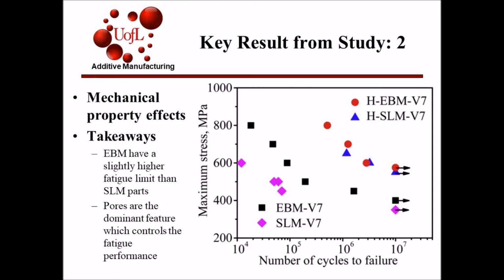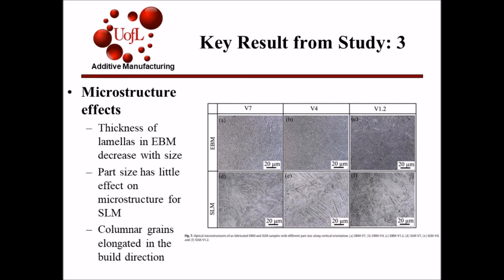It was also determined that pores were the dominant feature that controlled fatigue performance. This can be observed in the graph, as samples shown in red and blue that had pores sealed by heat treatment greatly outperformed those that were as-fabricated samples. Key results for microstructure effects.